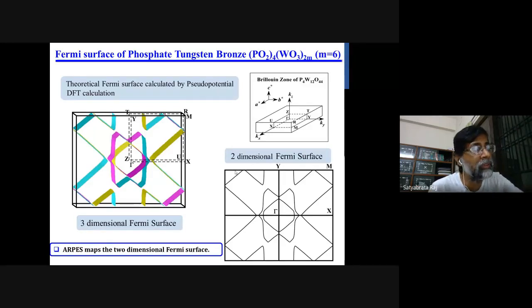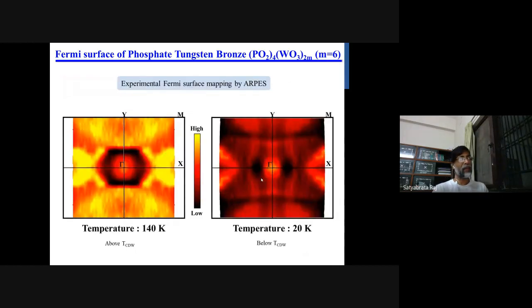We have taken the projection on the two-dimensional Fermi surface, and this is the two-dimensional Fermi surface, and ARPES maps the two-dimensional Fermi surface. To have a charge density wave, the Fermi surface should have a very straight patch which should be connected by a nesting vector. So now we measured the Fermi surface at two temperatures.